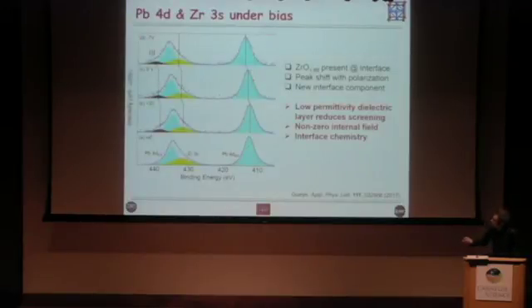These are the results. This, again, is the reference without the electrode. That's why the statistics are much better. Here's a bit noisier. We can see three things. First of all, this is the component due to the zirconium. It includes both the nanostructures and the zirconium in the first layers of the PZT. And these are the components due to the lead. What we see is that as the bias changes, the whole spectrum is shifted. Remember, we've corrected for the applied bias. So this is polarization due to internal field in the PZT.